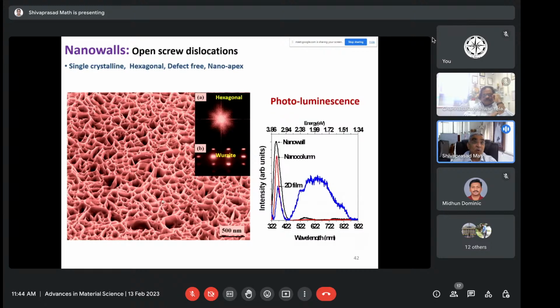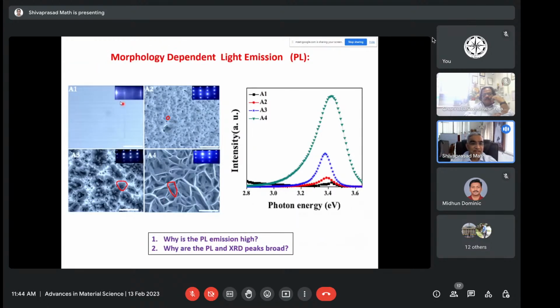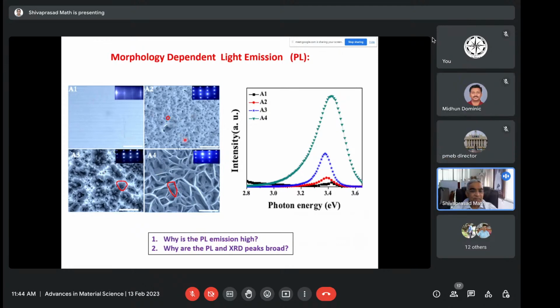I'll show you how the convergence of semiconductors and nanomaterials has given rise to amazing properties which we never thought could have happened. That's why it kept us engaged for nearly five to seven years. Just this material. We stopped doing everything else and started looking at this material. Say, for example, see here, this is a gallium nitride film, the commercial film. And this is what we have grown, and they are different. We have grown all these kinds of films here.